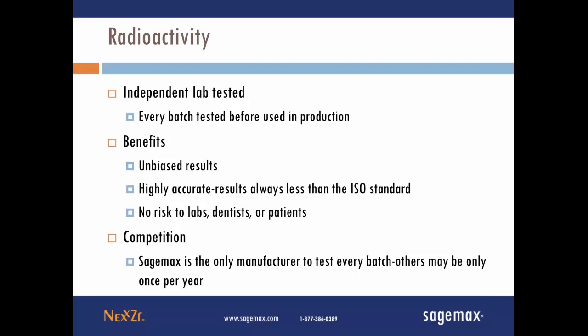I just want to add here that we want to make sure that we provide very accurate data to our clients and that they feel very safe using our materials. Needless to say, sometimes we cannot get a lot of this data from our competition. And what we've seen actually in the last year is a lab in Taiwan had actually gotten some zirconia from China. When it was tested, it was 4.5 times what the ISO limit was. So of course we know that's something that's very dangerous, and like I said, it's something that's important to us that we rigorously screen. Also, I wanted to add here that we keep very good records of our testing. So if ever there is an issue of traceability, we can provide those results very, very quickly.